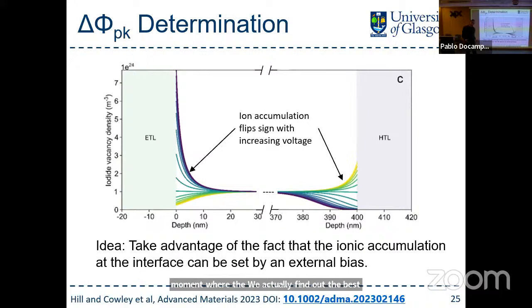Now, this is an interesting result because measuring the built-in potential of a cell is difficult. You normally have to do something like UPS layer by layer, or build some very complicated Kelvin probe setup where you find the potential of the surface and so on and so forth. We can do this in a device, which is quite neat because then we don't have to make assumptions. This is what it is.